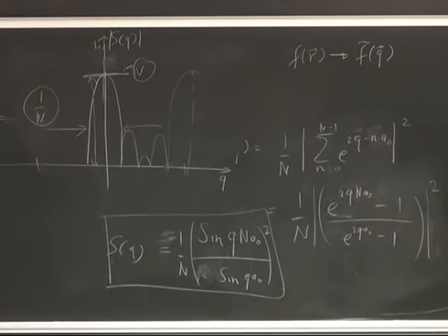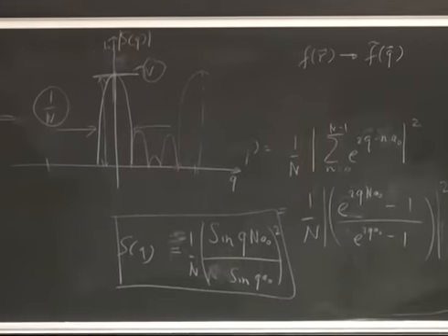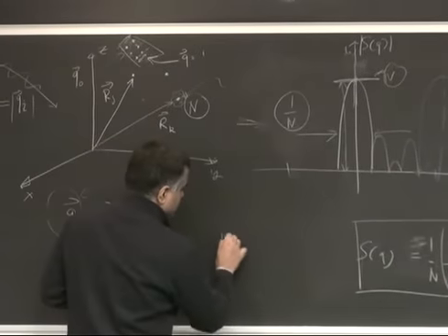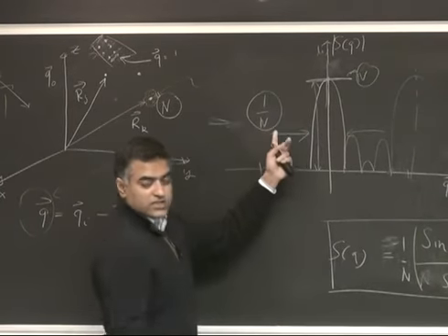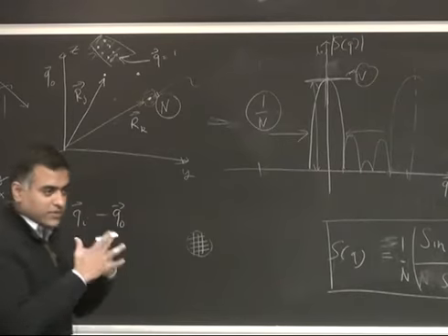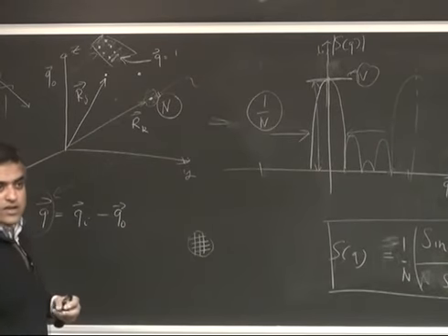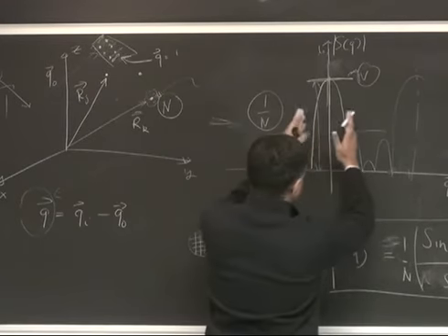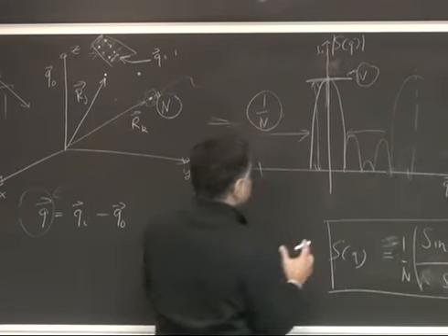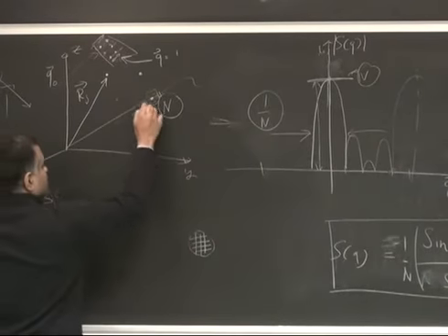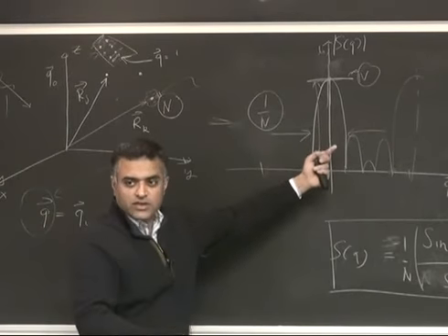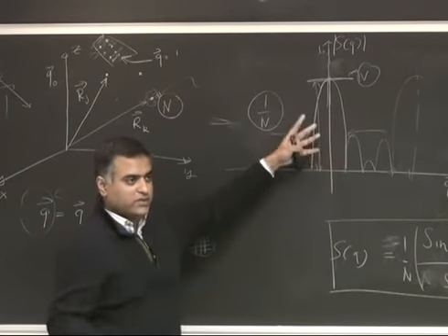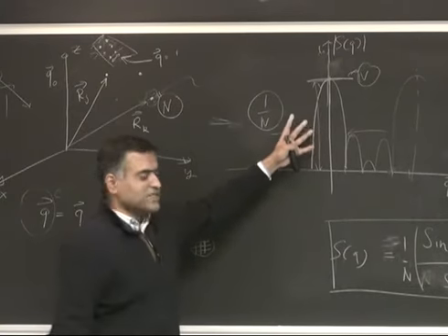From the width, you can say, for example, what's the size of the nanocrystal, if it's perfect. If you have a 5 nanometer nanocrystal, which is composed of, say, 1,000 atoms, you can start looking at 1 over 1,000 here compared to a very large number for solids. So you can measure that from looking at the widths carefully. If you have a distribution of many nanocrystals of different sizes, you can add them all up separately. Always add the amplitudes and then take the mod square, and you can figure out more information about the solid.